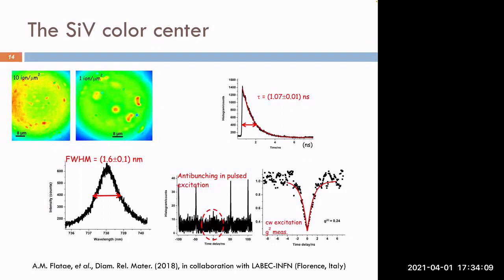So in principle, you could get gigahertz emission from these kinds of sources. So this will be really competitive with laser systems for single photon emission. And then, of course, the big question is whether these are single photons or not. And as I told you, then you go for this Hanbury Brown and Twiss setup in pulsed excitation or in continuous wave excitation. And what you should expect is a dip when you have zero time delay between the two detectors. And this is what we get. And this shows that we can have single photon emission from the silicon vacancy center.